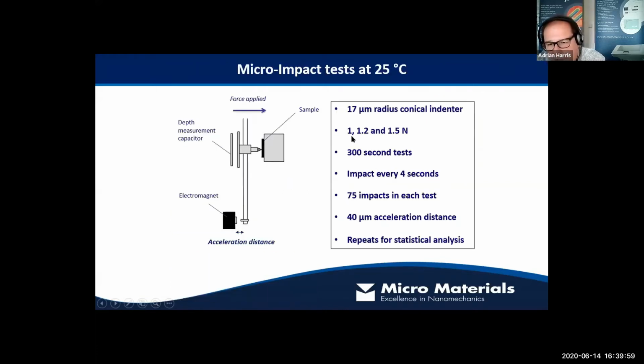So, to the impact tester. For the impact test, we use a 17 micron radius conical probe. This is actually a spheroconical tip. It's a cone of 90 degrees that terminates in a spherical cap. It would have been a nominally 25 micron tip, but we measure these things very accurately, and this is actually more like 17 microns radius.